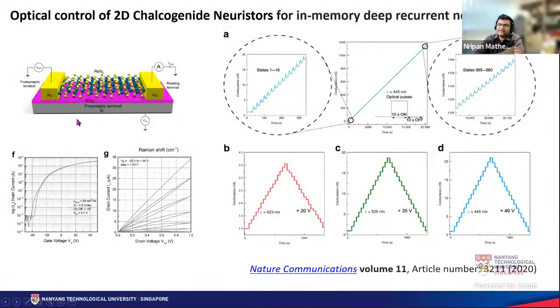We actually went ahead and did even more work. In this work, we used rhenium sulfide transistors. Again, conventionally their mobilities are 26, etc. But what we found were persistent photocurrent effects in these systems. Once you shine the light or apply an optical pulse to it, the current initially spikes, as shown here, and then kind of saturates. And this control can be very nicely performed.